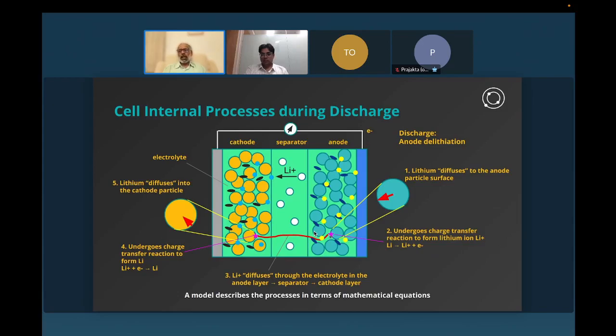And when it sees the electrolyte, the lithium then decomposes to give Li+, which is a lithium ion, and an electron. So that's the reaction that happens at the surface of the anode particle when the lithium migrates to the periphery.